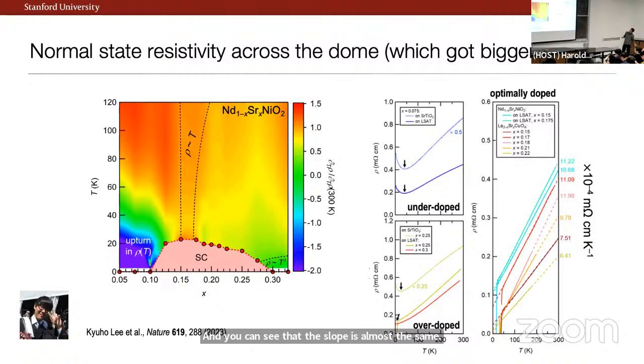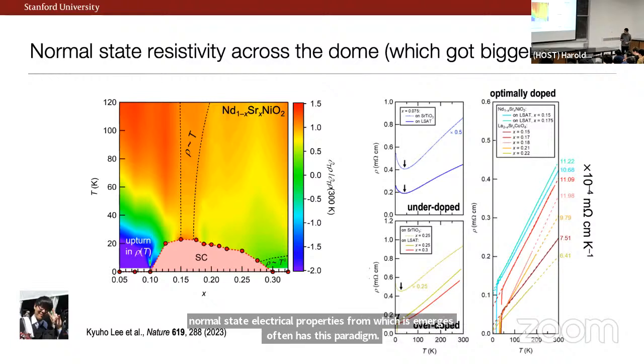So as we dope from one side of the dome to the other, we find in the heavily overdoped side something that looks like a normal Fermi liquid metal. Namely, we see a resistivity that varies as T squared. And then on the underdoped side, we have this characteristic logarithmic-like upturn. What's interesting is that possibly in this lecture room, you may have seen this kind of data for cuprates, for 2D systems. And so this is a very common motif that in the proximity of an unconventional superconductor, the normal state electrical properties from which it emerges often have this paradigm. And so it was very interesting to us to think about this in more detail.